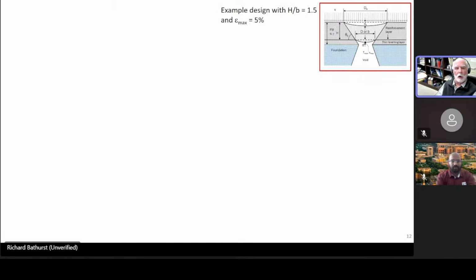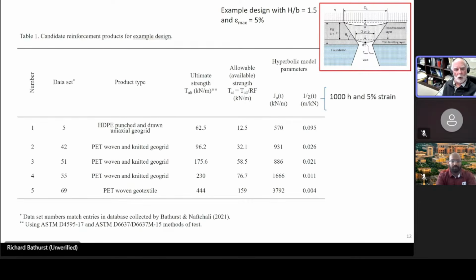So here's an example of how one can carry out a design for a particular problem, in which the height of the fill to the ratio of the void width is 1.5, and we're designing to a maximum strain in the reinforcement of 5%. So here in this table are the properties, the ultimate strength and stiffness properties of 5 candidate reinforcement materials for this particular problem. And the hyperbolic model parameters are shown here for 1,000 hours and 5% strain.